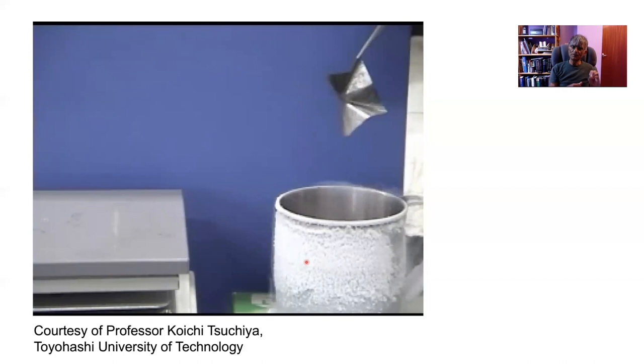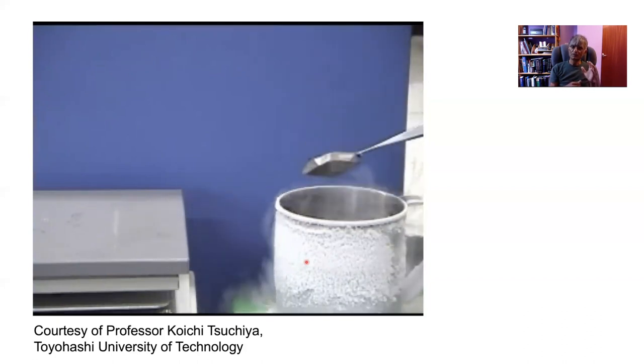Now, the key point is that you need to regard martensite as a combination of a crystal structure change and a deformation. Slip and twinning simply cause a deformation. They do not change the crystal structure. Martensitic transformation actually deforms and in the process the crystal structure changes. So you can regard martensite as a deformation mechanism, and it turns out that that is a very important characteristic which is used in the design of extremely ductile steels, we will see in a later lecture.